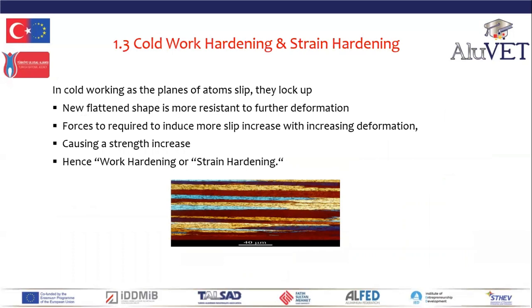During cold working, as the degree of slip increases with increasing cold work, the deformation of the grains becomes more severe. Eventually, the deformation of the grains is so severe that it causes the planes of atoms to lock up. Locking up of the planes resists further deformation. So the force to slip the planes of atoms increases.